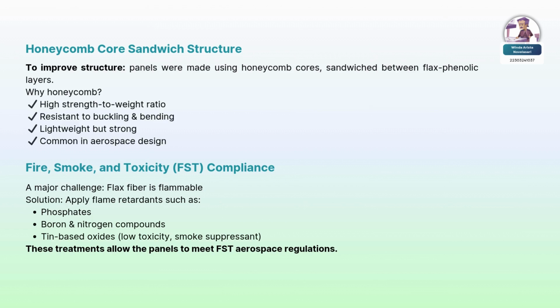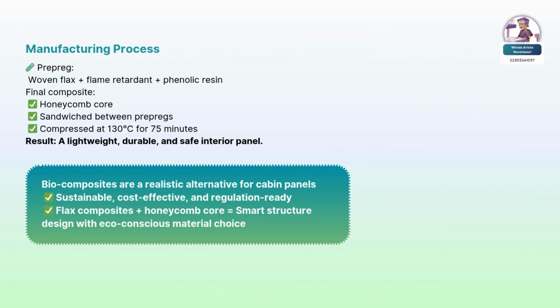But the big hurdle was meeting fire, smoke, and toxicity standards. Since flax is flammable, flame retardants like phosphates or tin compounds were used. This helped the composite meet FST regulations safely. In the manufacturing process, they first created flame-retardant flax-based prepregs, then sandwiched them with honeycomb cores. Finally, they used compression molding at 130 degrees Celsius for 75 minutes.